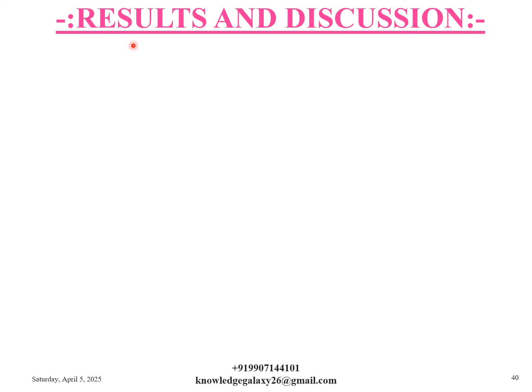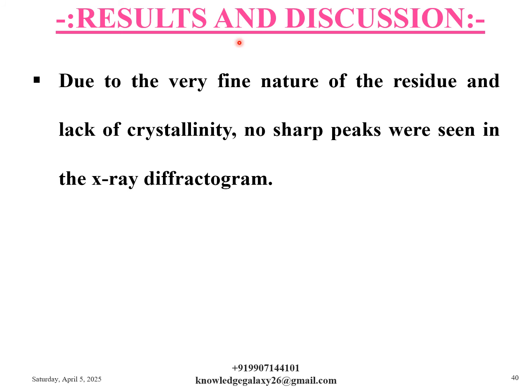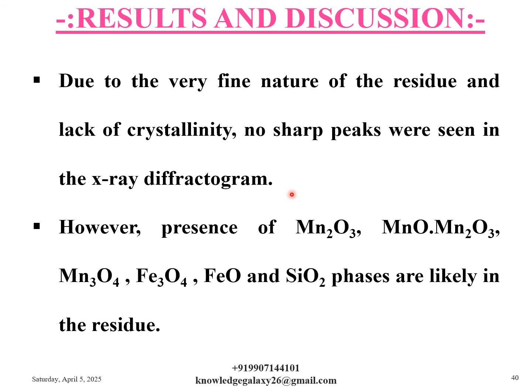So now we have come to results and some more discussions. Due to the very fine nature of the residue and lack of crystallinity, no sharp peaks were seen in the X-ray diffractogram. However, the presence of Mn2O3, MnO.Mn2O3, Mn3O4, Fe3O4, FeO and SiO2 phases is likely in the residue.